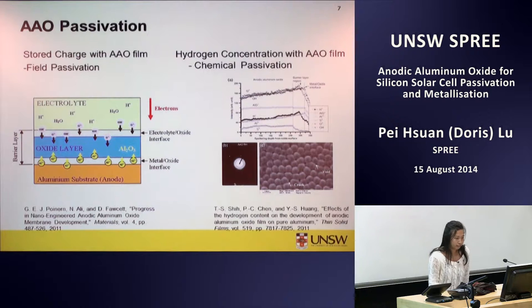So people have done lots of things to analyze the porous layer. We can see there is a high concentration of hydroxy ions and oxygen ions in the AAO film, which is a porous layer, and you reach the peak at the interface at the barrier layer.